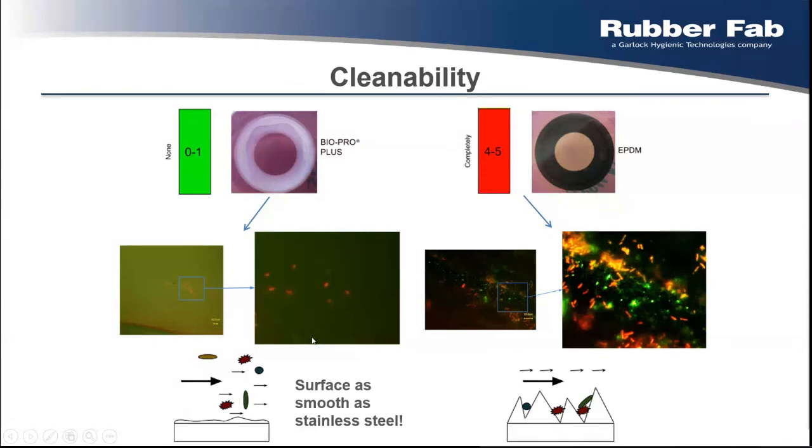What we actually confirmed, by using the fluorescence microscope, was that the surface is very clean with only very minor organic residues, which are very likely to represent fats. In this case, we can be very sure that there are no organisms because of the very specific shape of the test organisms used. They're like long worms almost, as you can see in this picture very well. So we have confirmed that the cleanability of GYLON Bio-PRO Plus was successful through all of our testing.